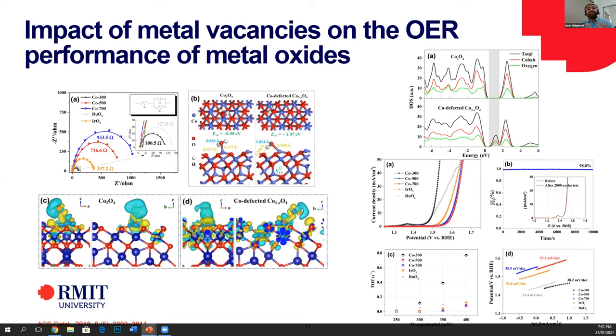When we explored that, we found that we are still getting a very high oxidation state in our system. The EXAFS and XPS studies prove it, and then we did some DFT studies that also found that such a disruption creates more favorable sites for the water molecule to adsorb and perform the oxygen evolution reaction. Ultimately, we found that they are even better than what traditional noble metals can do, and very stable and very effective for the oxygen evolution reaction.